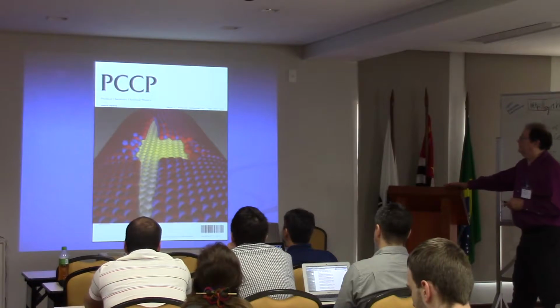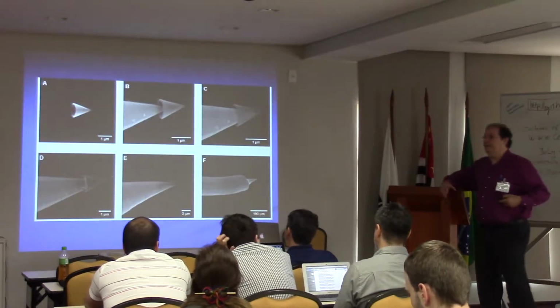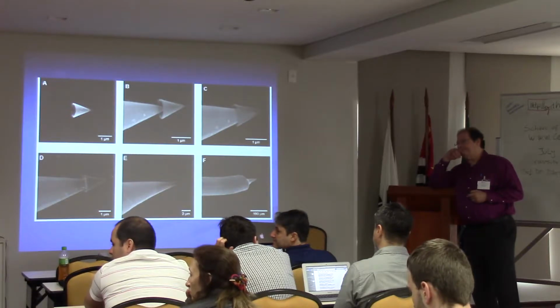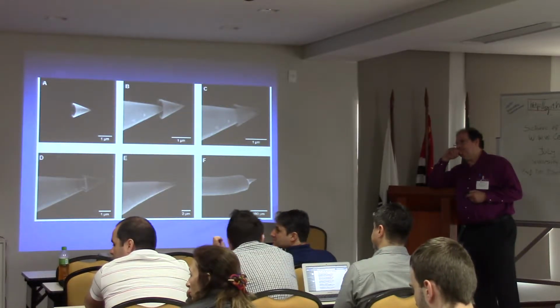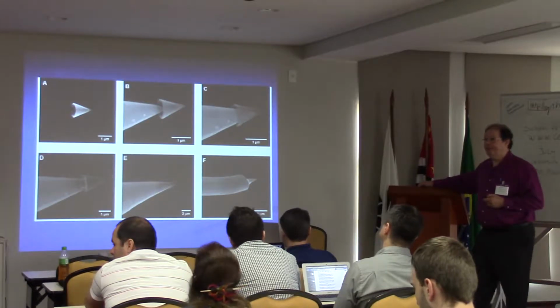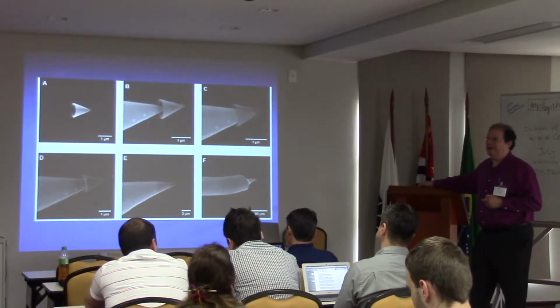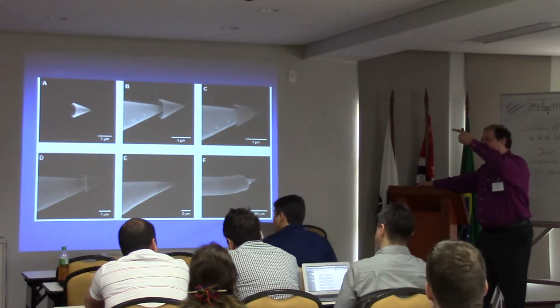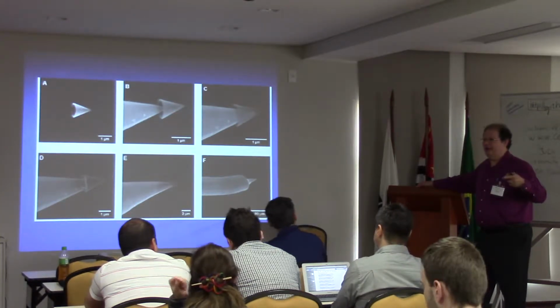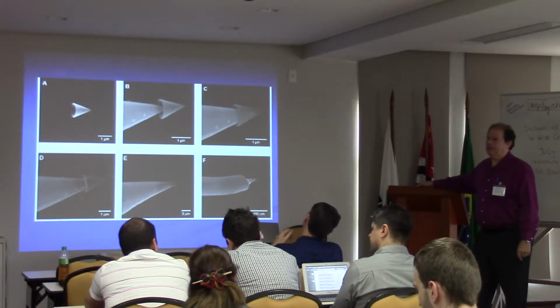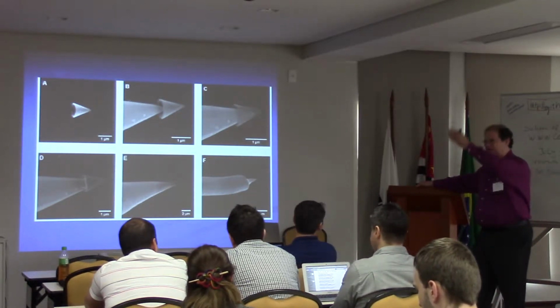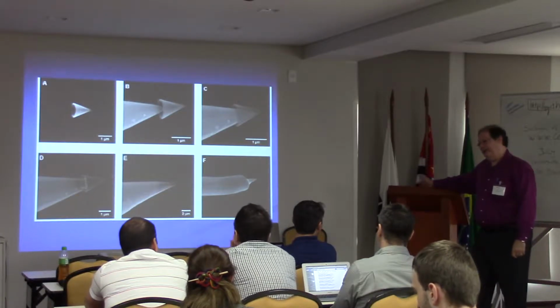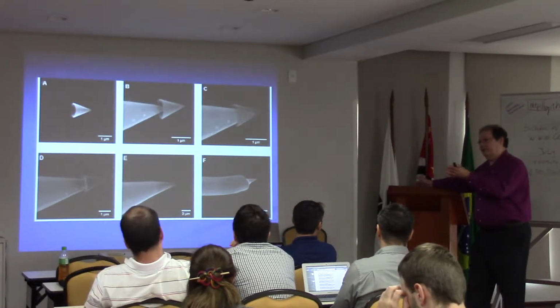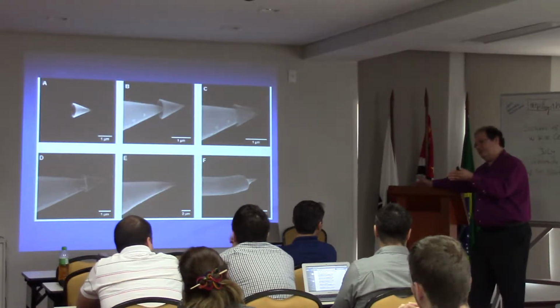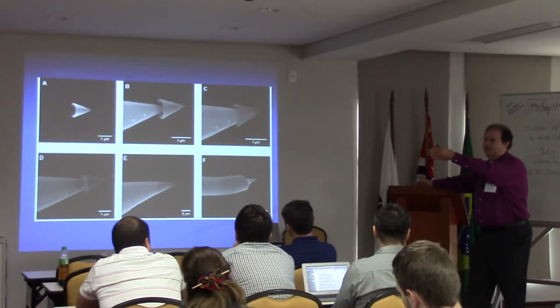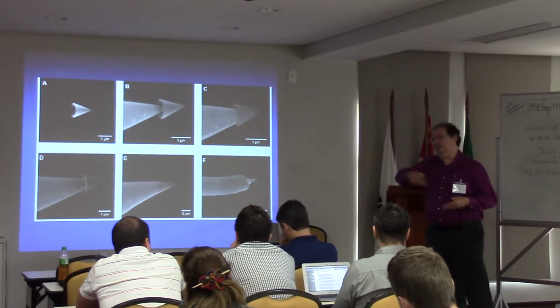It was again a cover of the PCCP. The pattern is not random, it depends on whether it is armchair or zigzag. In one case, you have very clean cuts. In the other case, you have this random, rough cut. But in the case of the armchair, you have a very clean cut. And in the experiment, they also see this distinction. They cannot tell you which tube is which, but they observed clean cuts and random cuts.